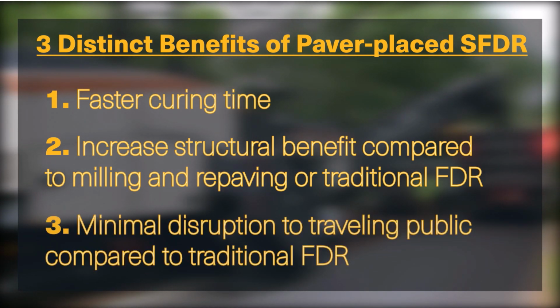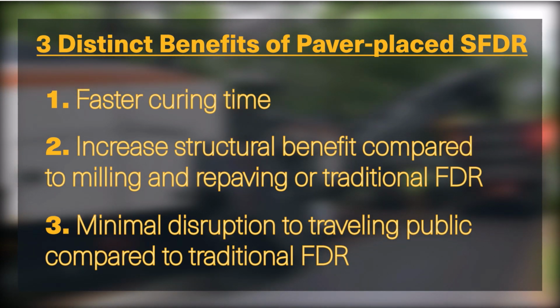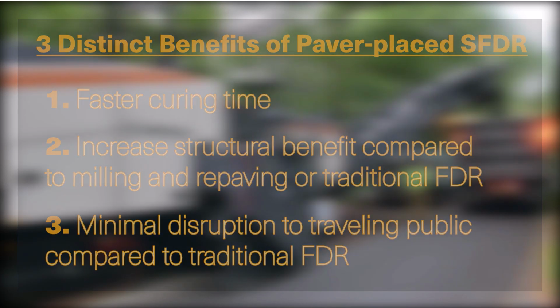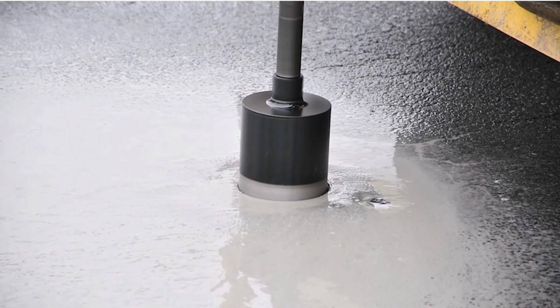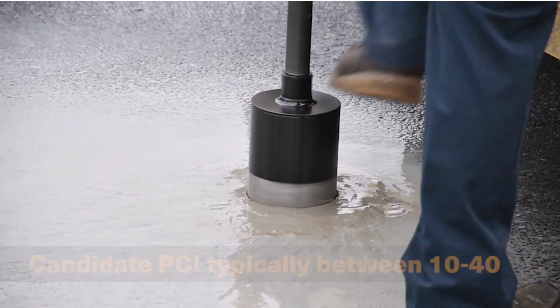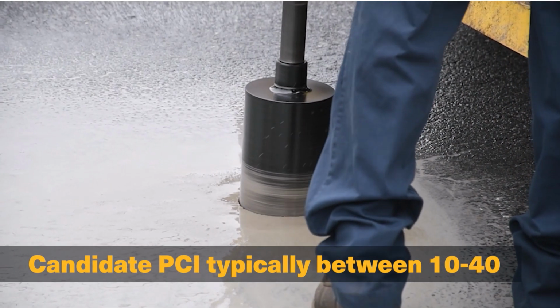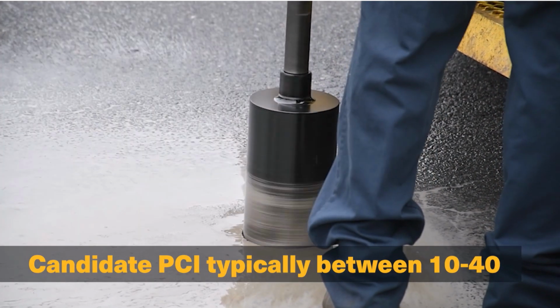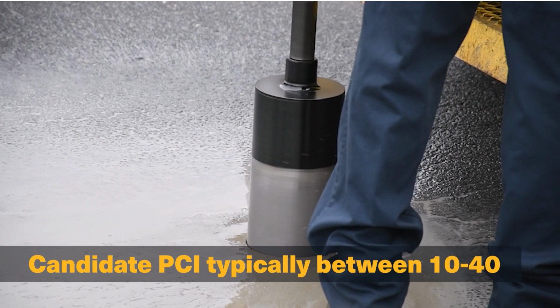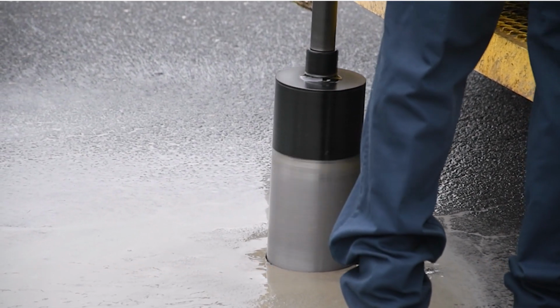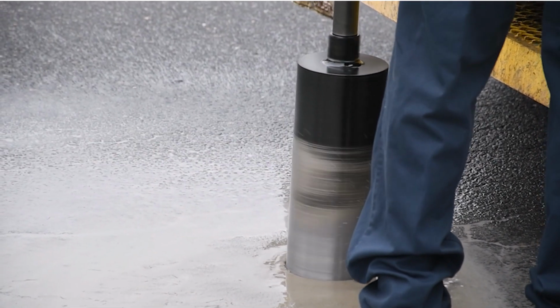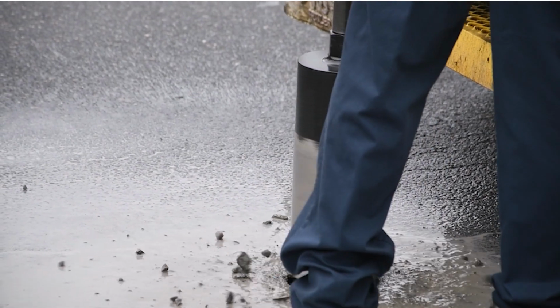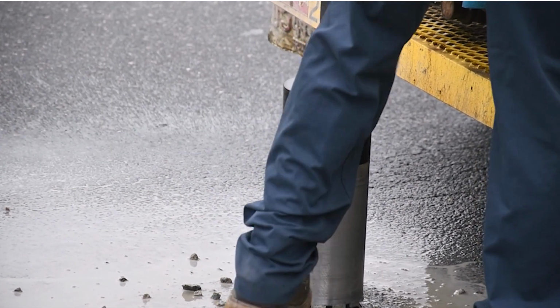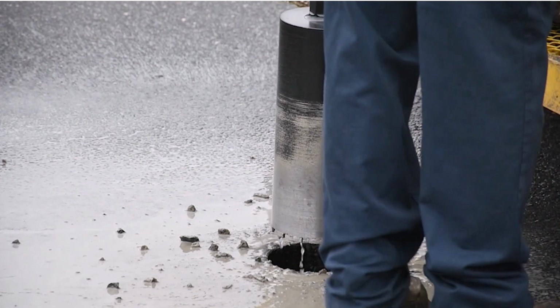3. Minimal disruption to the traveling public compared to traditional FDR that typically requires windrows and the use of a grader. Candidates for the paver-placed stabilized FDR process are cored extensively to determine the appropriate recycling depth. These cores are then processed and analyzed by an independent accredited lab to develop a job mix formula which prescribes the proper amount of asphalt and Portland cement additives to be blended into the pulverized pavement and underlying subbase mixture.